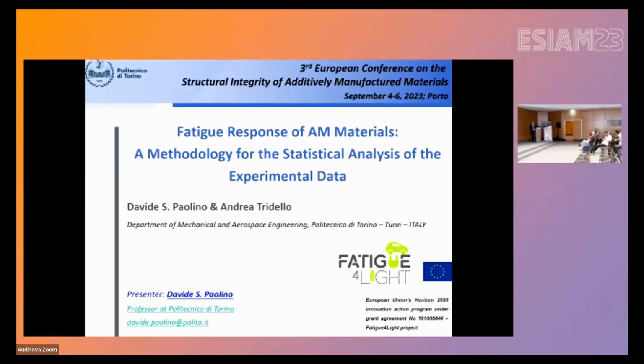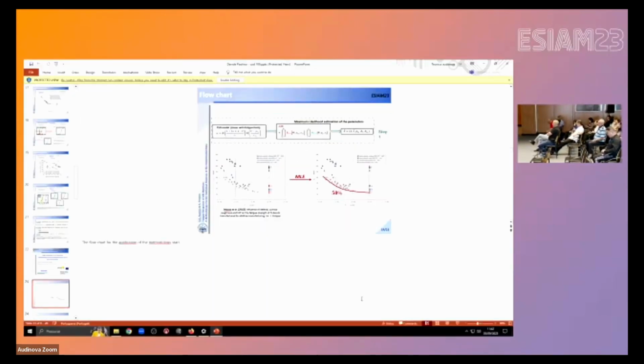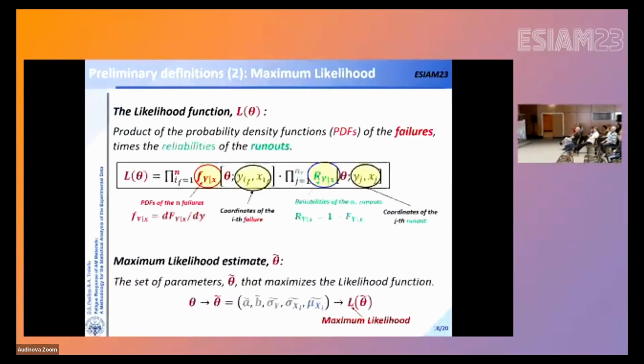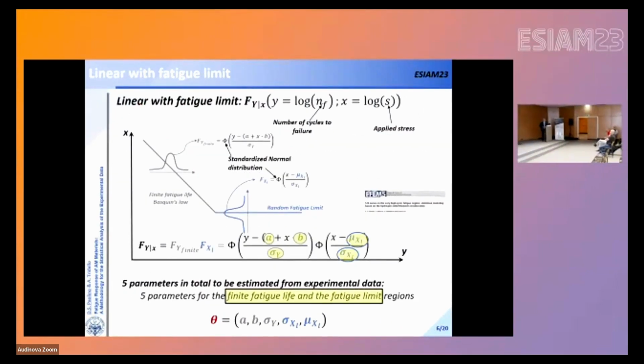Yes, thank you for an interesting approach. My question is, when you define the statistical parameters, on slide 7 if I remember, you use standard deviation. Standard deviation is the average deviation from all data. Deviation of experimental data in fatigue is not distributed regularly through the whole lifetime. In low cycle fatigue the deviation is relatively small, and in high cycle fatigue relatively large. Is it possible to take this fact into account, for example, by estimating level by level of stress amplitude, not on the whole line, in the whole region of lifetime, but on the level of stress amplitude? I don't know if this is only an idea.